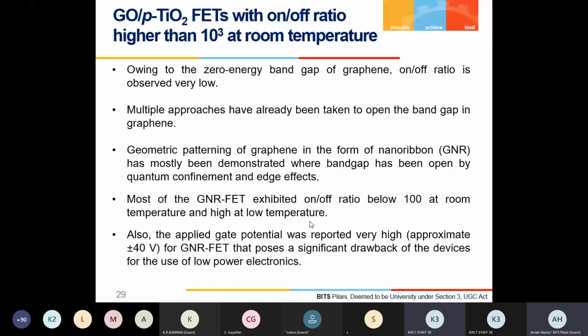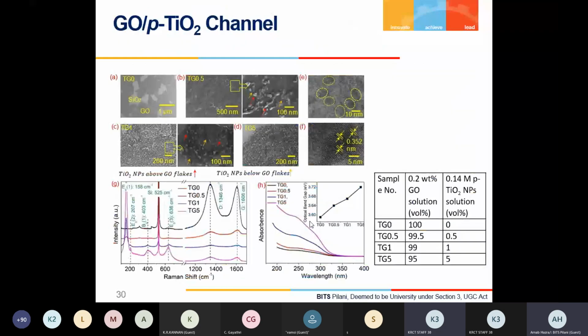So in this context, our research is showing a hybrid graphene channel which can show quite a high on-off ratio. You can see here the material that we have fabricated as a channel material is a composite of graphene oxide and titanium dioxide nanoparticles. This is the pure graphene oxide FESEM, or scanning electron micrograph, I have already shown. And these are the composites. The table shows which type of composites they are.